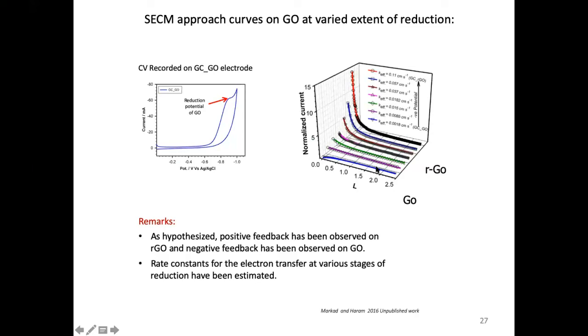These are the SECM measurements done on a graphene oxide film at various applied potentials. When the potential is low, I get negative feedback. That means my graphene oxide is still in the graphene oxide state. But when I keep on applying negative bias, graphene oxide is getting into reduced graphene oxide and I start getting positive feedback, which indicates it is conducting. It's a very nice illustration of how SECM can be used for all these purposes.